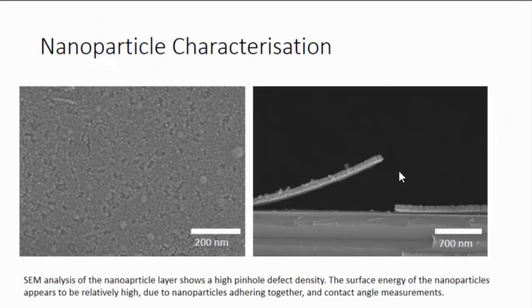So when observing the nanoparticles from above, we found that our nanoparticles had an average diameter of about 22 nanometers, and they actually had a really high surface energy for what we expected. They were able to hold together into a layer, and contact angle measurements revealed that they had an extremely hydrophilic type behavior. We also noted that there is a pretty high density of pinhole defects in one single sheet of nanoparticles. So that could be one reason why our periodicity versus thermal conductivity did not have a particularly strong correlation. We don't have a way of assessing what the defects are through multiple layers. So that could be one reason why we didn't see as strong a correlation as other people have reported.